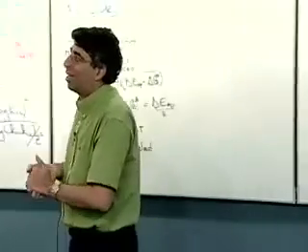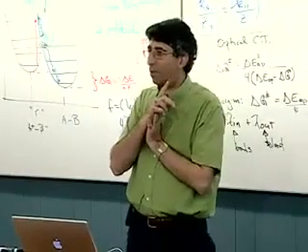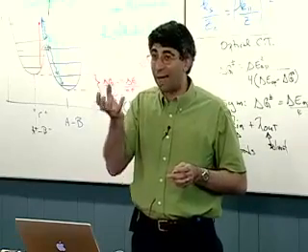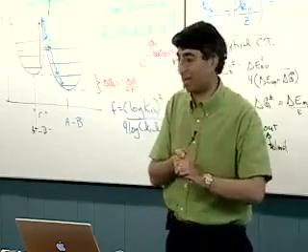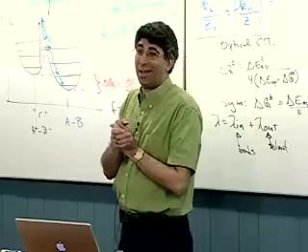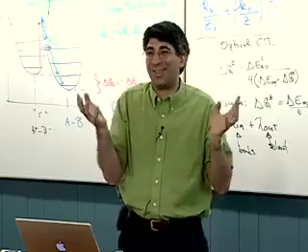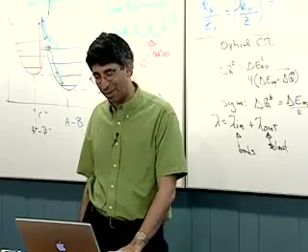but of course it doesn't mean anything, because I don't really know how many waters it's lost. Okay. There were some nice experiments that Dan Buttry did on this system, who used a quartz crystal microbalance to actually assess the mass of these ions going in. It's very sensitive, and he can tell you something about the number of waters. And the simple answer is some of the waters fall off when it goes into the lattice. But you cannot nail the problem this way.